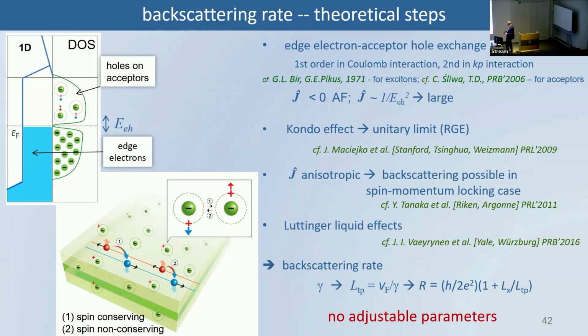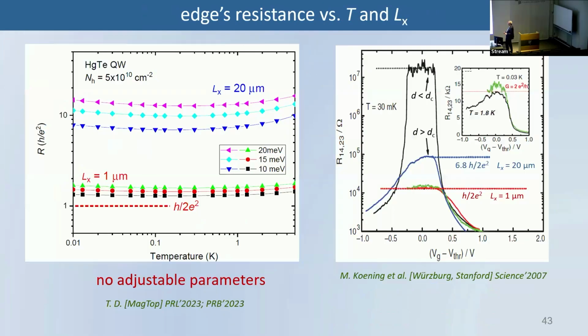So you can calculate per second how many events of this transition between this state and that state can occur. And doing all that, you end up with a theory with no adjustable parameter. Here you have calculation for a few values of distance between electron edge states and holes on acceptors. It depends a little bit, but not too much. And you see that for a 1 micron sample, you expect a value which is close to quantization, as expected here.